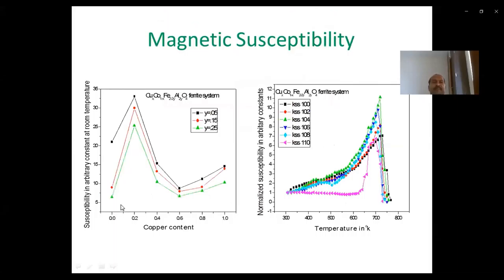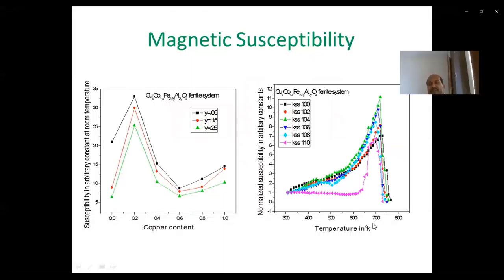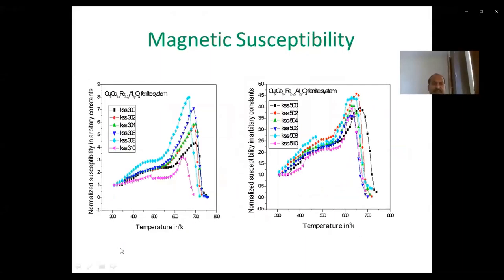In the case of magnetic susceptibility, it increases up to a certain value of the copper content, and then goes on decreasing. In the case of temperature also, for a particular population, the susceptibility goes on increasing and decreasing, but as temperature increases, this peak temperature shifts towards the shorter temperature side.